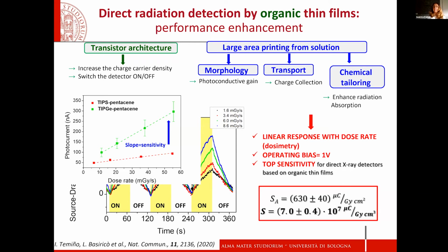The message here is that you see a very nice linear response that tells you that these materials can be used as actual dosimeters in real time. The operating bias is very low, about 1 volt. The sensitivity is really good, beyond the state of the art, as I was showing you in the beginning, in the review graph. And here, what I wanted to show you is how the slope, which is the sensitivity, changes by simply changing one atom in the TIPS molecule. So again, these are the first results, but I think this opens a very nice perspective for future advanced material development.